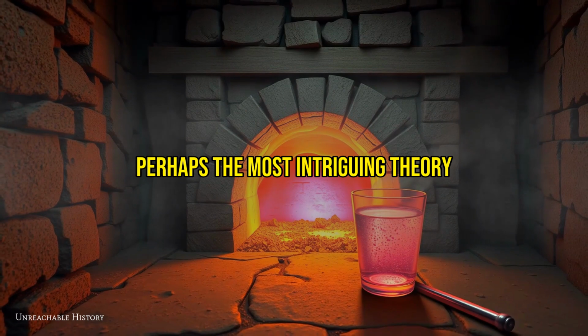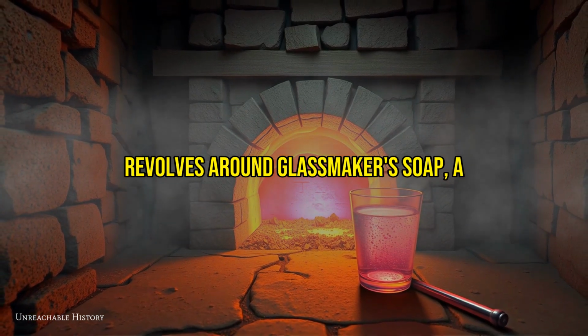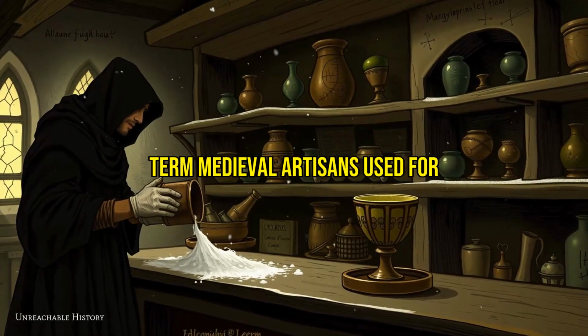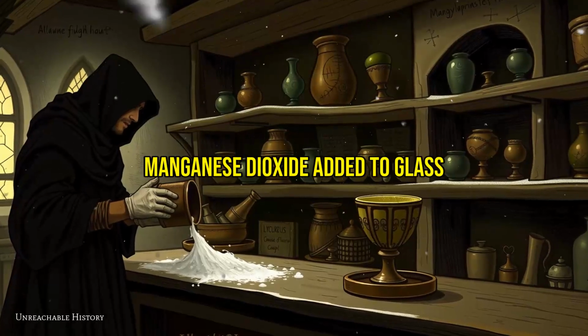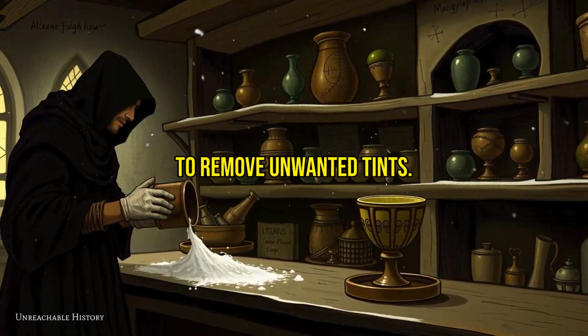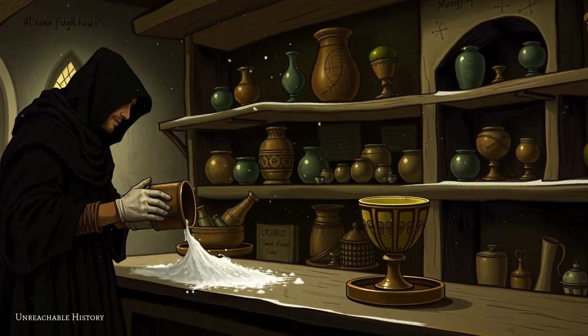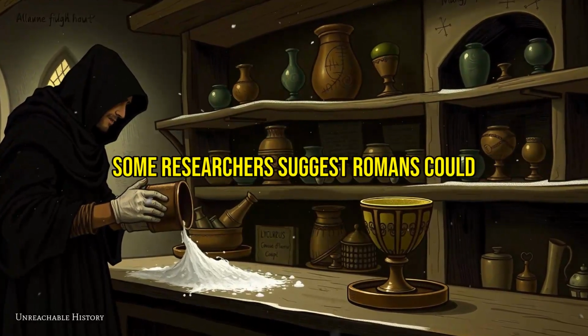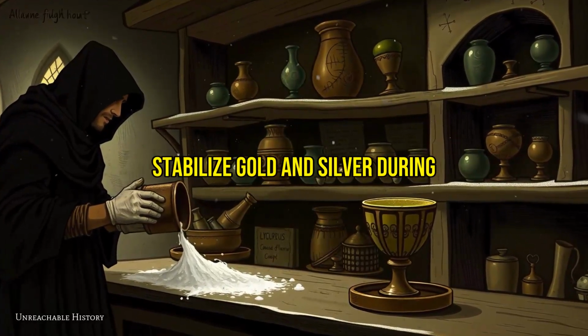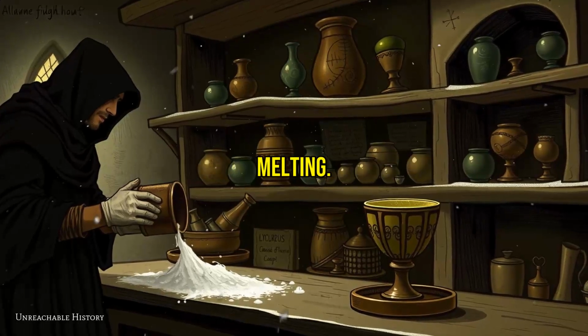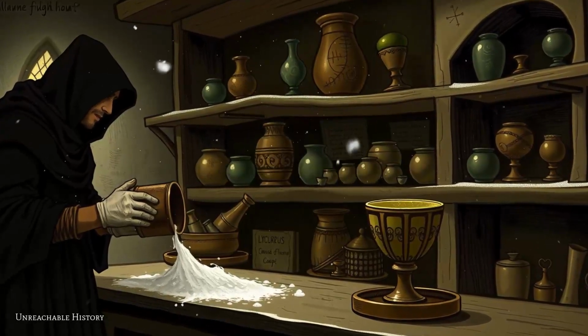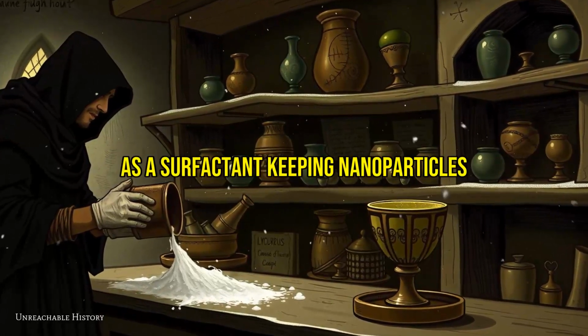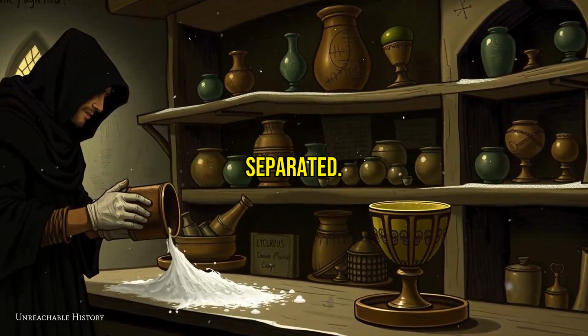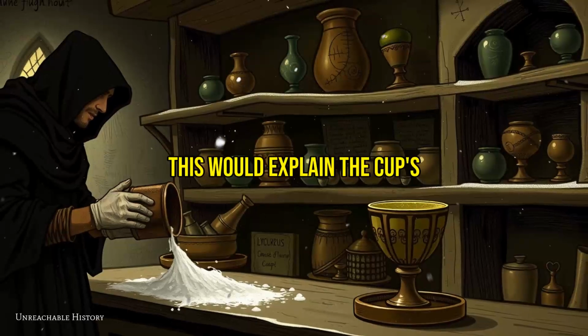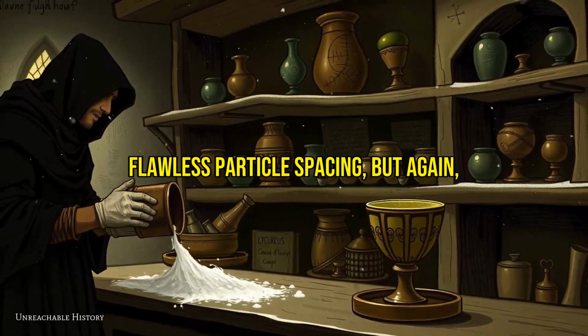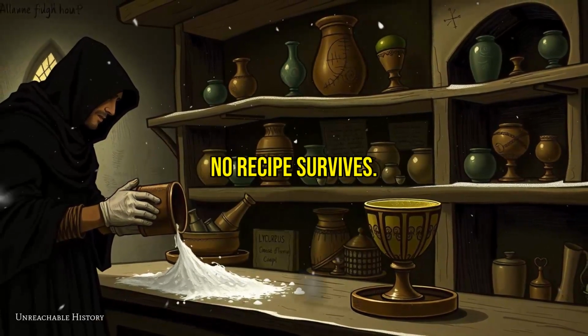Perhaps the most intriguing theory revolves around glassmaker's soap, a term medieval artisans used for manganese dioxide, added to glass to remove unwanted tints. Some researchers suggest Romans could have used similar additives to stabilize gold and silver during melting. A pinch of tin or lead, for instance, might act as a surfactant, keeping nanoparticles separated. This would explain the cup's flawless particle spacing, but again, no recipe survives.